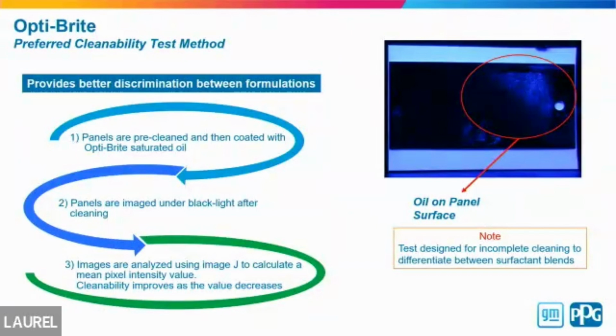Cleanability is another thing that we are going to screen, because that's what a cleaner is supposed to do, clean and remove everything, the oil in this case. Typically you look at the water break to assess the efficacy of a cleaner. For our development, our preferred method was the OptiBright. OptiBright is similar to a carbon mapping. Basically, we took a panel, we cleaned it, then we mixed the oil that we're trying to target, or the mixture of oils, with a dye. Then we applied this oil doped with dye on the surface of the panels.